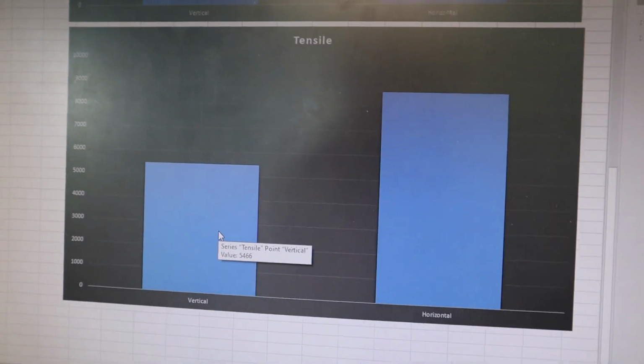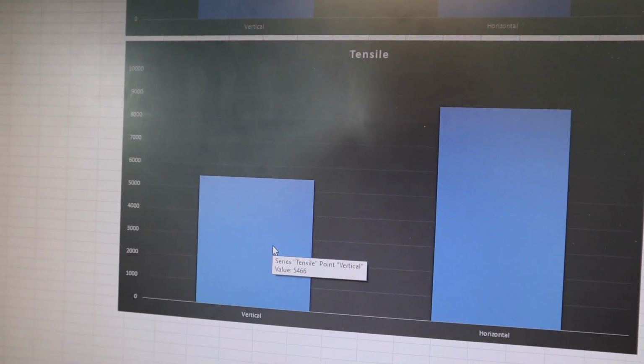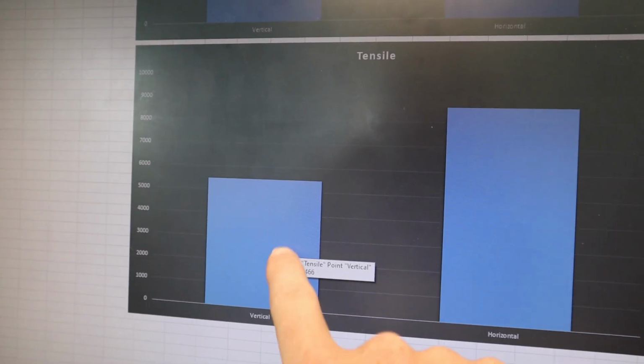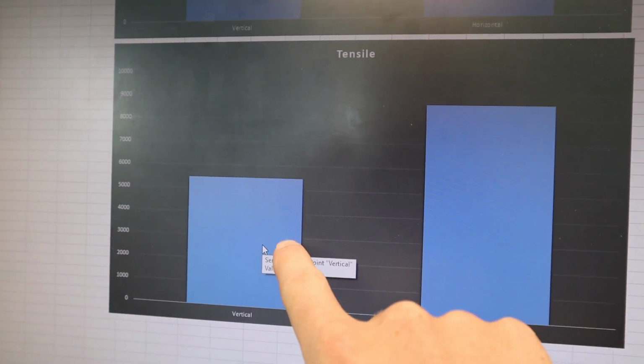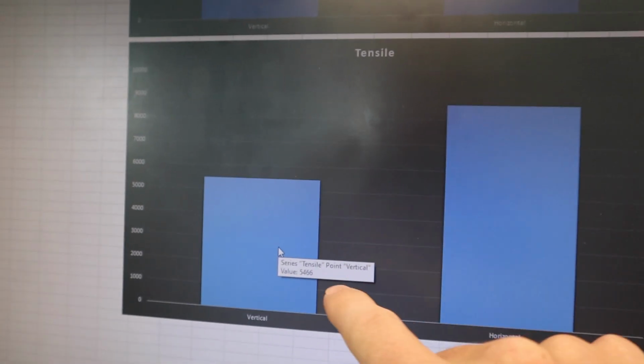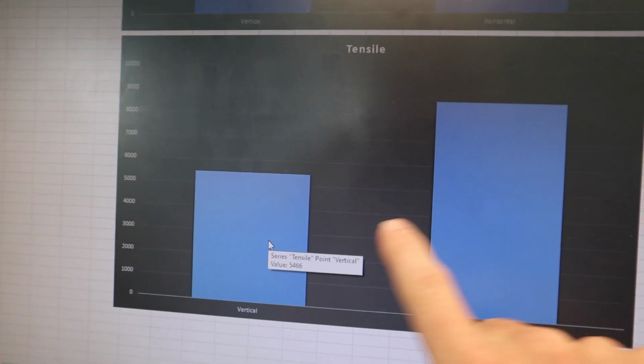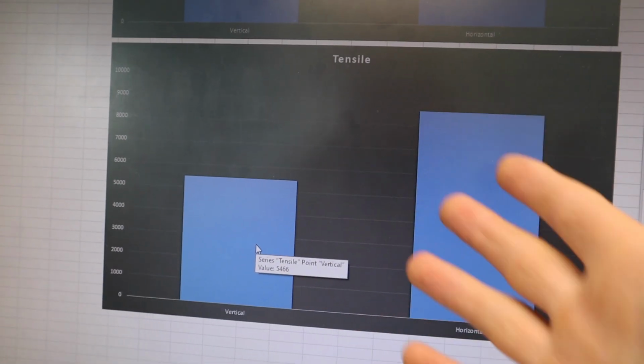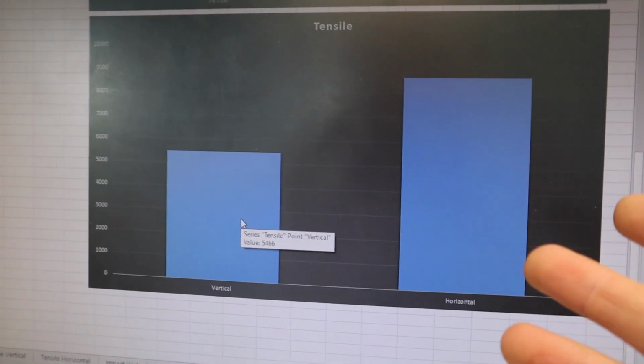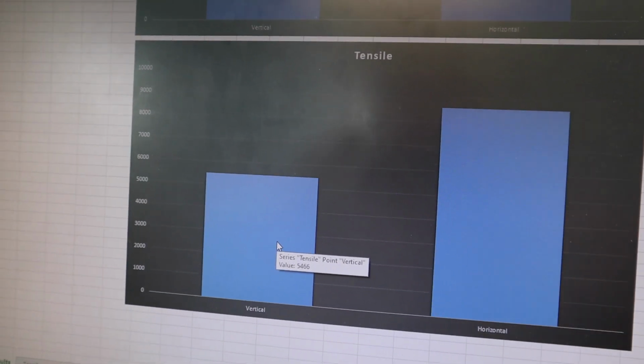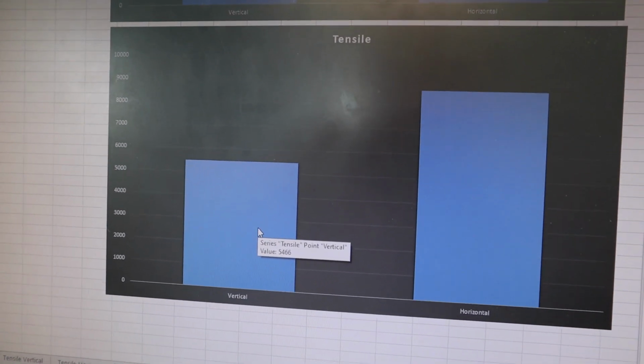This is the tensile strength, and you can see that the vertical test sample with layer adhesion was actually more than 50% the strength by quite a bit. It was 5,500 compared to 8,500 PSI tensile strength, and so that was actually pretty good. Now, just looking at these results isn't very helpful without being able to compare them with other filaments. So I'll be doing more testing, and then we can compare it, and it'll be more useful.